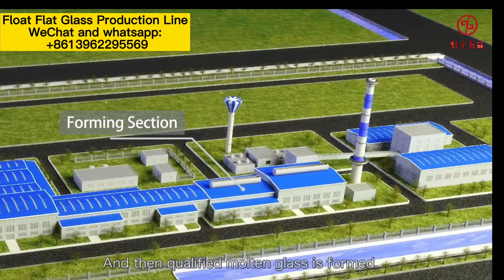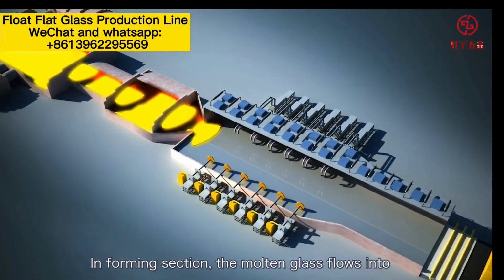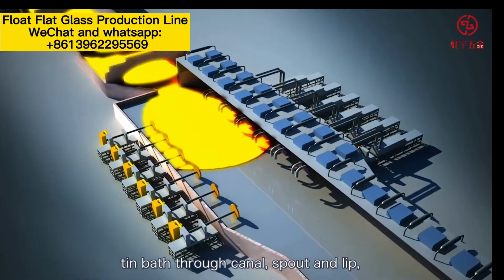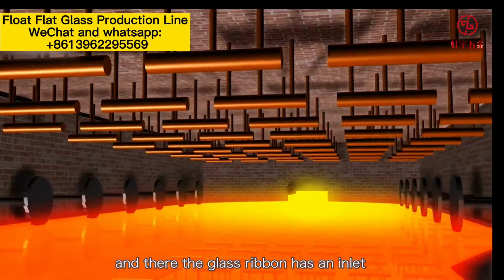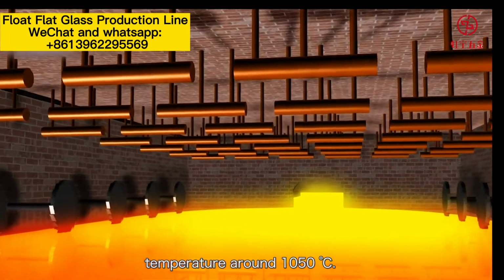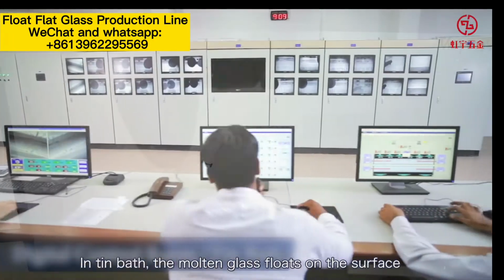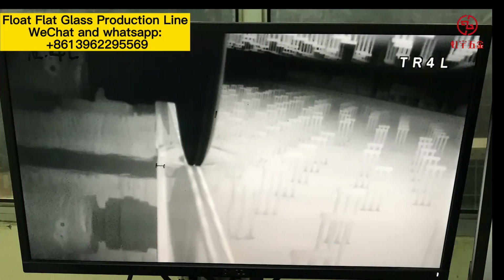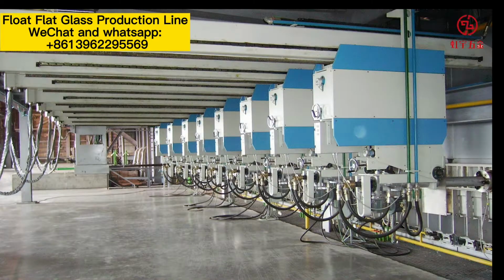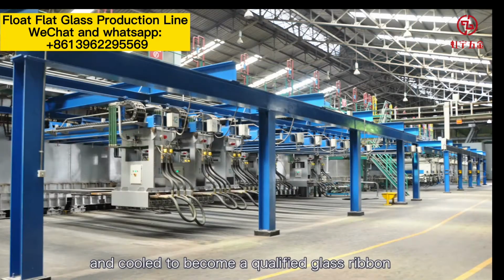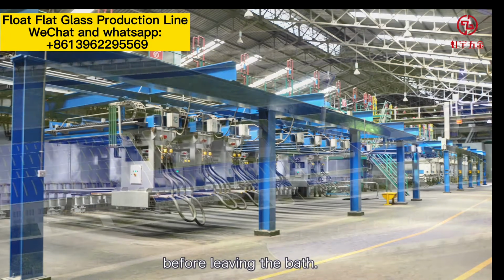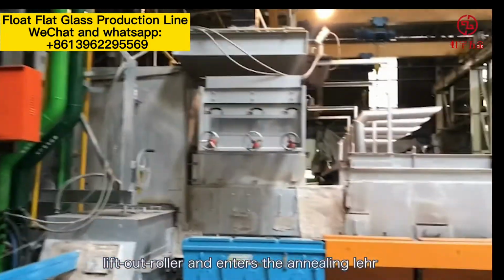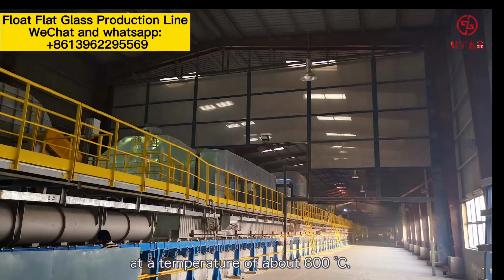In forming section, the molten glass flows into tin bath through canal, spout, and lip, and there the glass ribbon has an inlet temperature around 1,050 degrees Celsius. In tin bath, the molten glass floats on the surface of the tin liquid to be flattened, polished, thinned, and cooled to become a qualified glass ribbon before leaving the bath. Afterwards, the glass ribbon passes through the lift-out roller and enters the annealing lehr at a temperature of about 600 degrees Celsius.